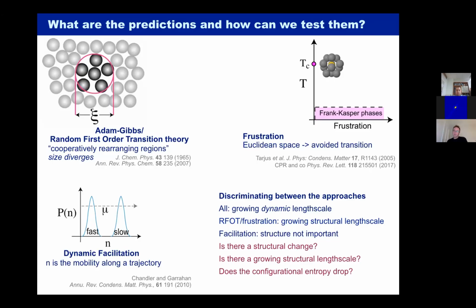And so if we look at what these predictions mean, just to be clear, the Adam-Gibbs interpretation and geometric frustration are both thermodynamic interpretations. Dynamic facilitation is a purely dynamic interpretation. All of them imagine a growing dynamic length scale. That is to say, the colored regions in the movie I just showed will get larger and larger as we reduce the temperature. The top two theories, the thermodynamic theories, imagine there's a change in structure if we can measure it. And the geometric frustration picture imagines there's an increase in the population of icosahedra or similar structures.